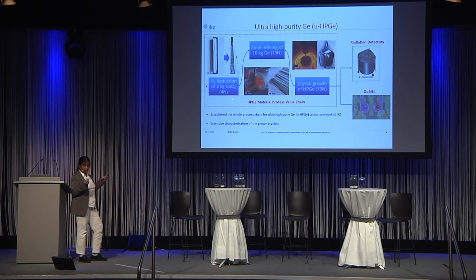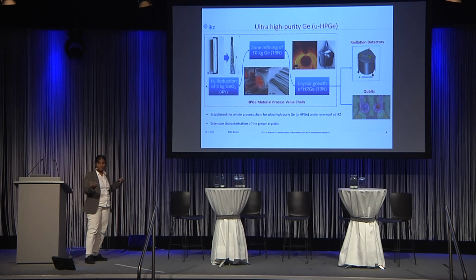It is only 4N pure, and we have to reduce it to a germanium metal, and then zone refine this metal up to a high purity, up to 13N purity. This is the highest purity one can achieve in germanium. And then after this purified material, we go to the crystal growth.